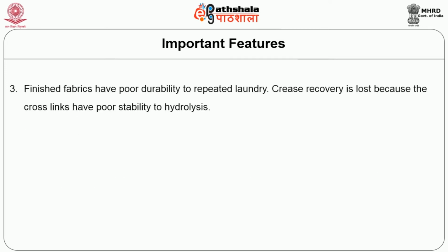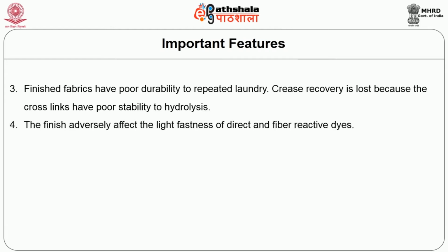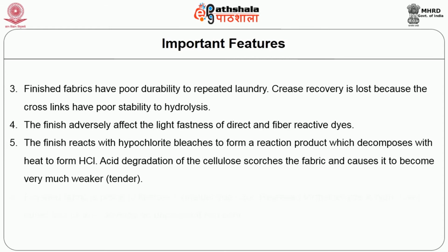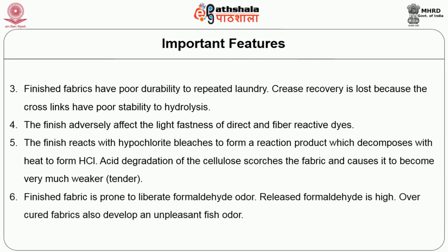Finished fabrics have poor durability to repeated laundering. Crease recovery is lost because the crosslinks have poor stability to hydrolysis. The finish adversely affects the light fastness of direct dyes and of some reactive dyes. The finish reacts with hypochlorite bleaches to form a reaction product which decomposes with heat to form hydrochloric acid. Degradation of the cellulose tenders the fabric and causes it to become very much weaker. Finished fabric is prone to liberate formaldehyde odor. Released formaldehyde is high. Overcured fabric also develops an unpleasant fish odor.